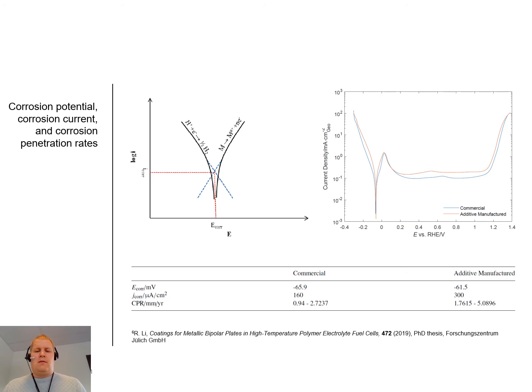This can be directly translated into so-called corrosion penetration rates, where you have for the commercial a value of between 0.94 to 2.7, while for the additive it is 1.7 to roughly 5. This is in correlation with the chronoamperometry measurements that we also did.